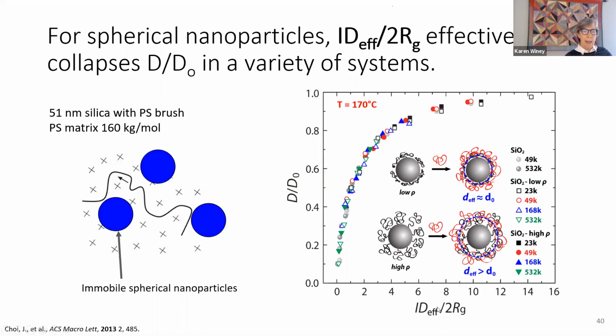And the only difference, the only correction that was made to get all this on one plot is that we used an effective interparticle distance, meaning we're taking into account, if you see the dashed blue circles here, we know the matrix polymer can only get so far into a grafted brush. And those calculations were done using self-consistent mean field theory. So we know how deep they can get in. And so everything else is impenetrable. So the D effective is bigger than the actual particle itself, but that's the impenetrable part.